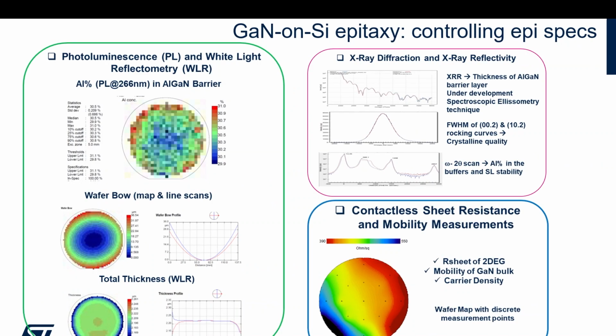So again, in a manufacturing environment, you need, first of all, to introduce the possibility to make measurements characterizing the epitaxy from the point of view of the barrier, or the point of view of the bow, from making the XRD in order to see the crystalline properties of the layer, and of course measuring by contactless means the resistivity of the 2D gas that gives you the conductivity properties of your final devices.